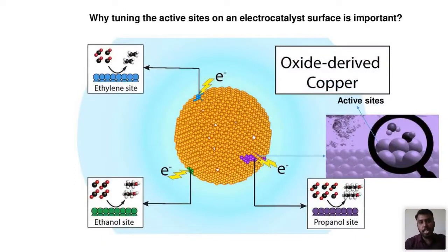Why do we need to tune the active sites? As I pointed out earlier, the active site is the particular site of interest where the electrocatalytic reaction will happen. So if you introduce more active sites, then the electrocatalytic activity or the kinetics can be improved. In this picture, you can observe there are different sites on a particle, like ethylene site, ethanol site, and propanol site.